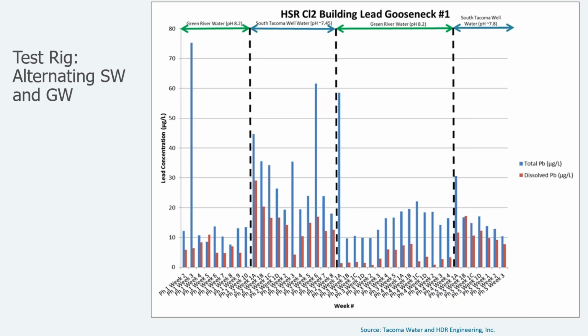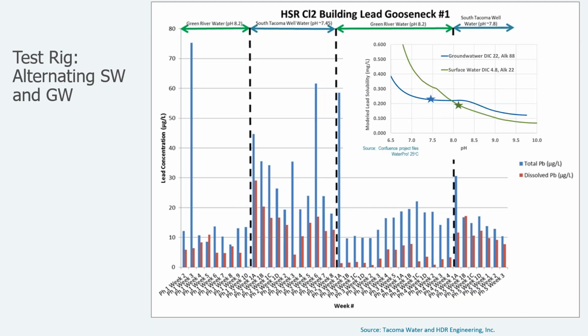particulate lead. And in phase one, when we're all surface water, we can see we're hovering around 10 micrograms per liter of lead. And then when we switched to the groundwater, we see a particulate release, much more particulate activity, and higher overall lead levels. Switch back to the surface water, a particulate release, and more particulate lead, because again, these scales are reequilibrating. And if we look at the overall solubility levels, lower in surface water, higher in groundwater, that is what the models predicted for the pH and DIC conditions of these waters.